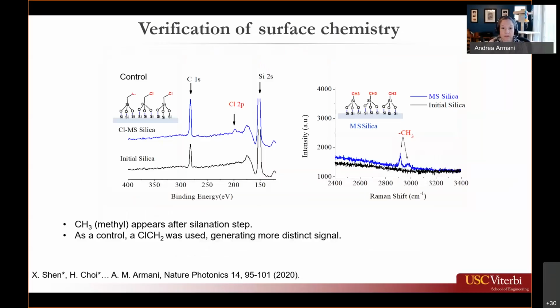So the first thing we did was to verify our surface chemistry. Our initial silica surface had a very classic silica XPS spectra. For the addition of the second layer, we did a control layer where, instead of a methyl group, we put on a chlorine functionalization, because chlorine would give us a very distinct signal. We were able to very clearly see the addition of that chlorine peak.